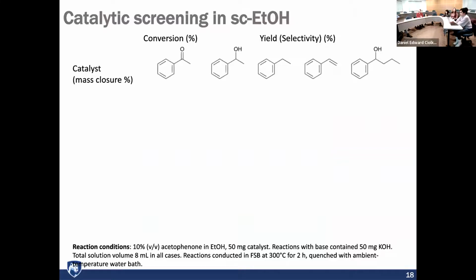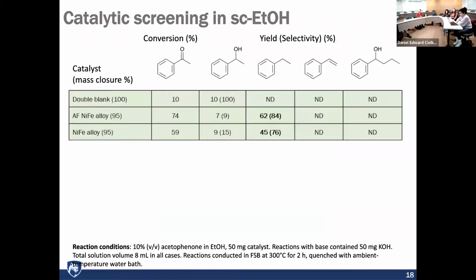So when we do this reaction, I have a graduate student who's screening all of these materials. And what he does is he just takes this model compound and he tries to do catalysis, and he tries to figure out, well, what's going on with our species here. So we look at the conversion, or we do a reaction. Here are the conditions down here. So we take 50 milligrams of our catalyst, 10 volume% of acetophenone, which is this compound. And we do this at 300 C for 2 hours, and then we quench it in ambient temperature.